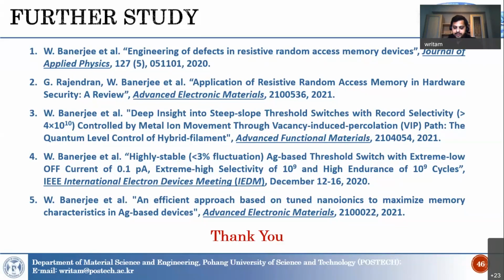The point is that we didn't perform that kind of experiment in this case because there are already plenty of reports available for TDDB, time dependent dielectric breakdown. The good part, or the easily understandable part of resistive switching devices, is that it is a soft breakdown process which can conduct the filament. There are plenty of references available which show that if you go through the gate dielectric, the conventional oxide devices, you can see that depending on the current level and voltage level, higher voltage can create more defects in the oxide.